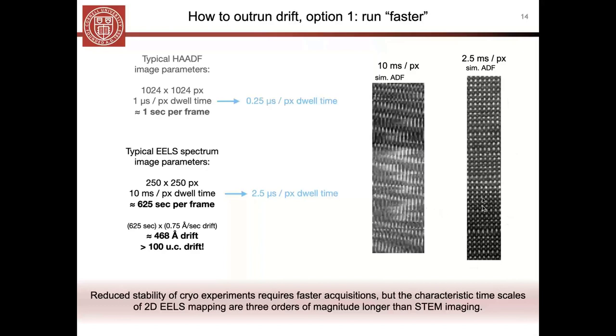And so that 4x improvement from the 10 to the 2.5 is really starting to get us towards this two-dimensional, spatially localized EELS mapping, which is where we want to go. And so it sounds pretty straightforward. Just turn down the dwell time on your camera and run faster with your EELS mapping. But in fact, what we've found is that once you get to these very fast readouts, you enter a sort of inherently signal limited regime.